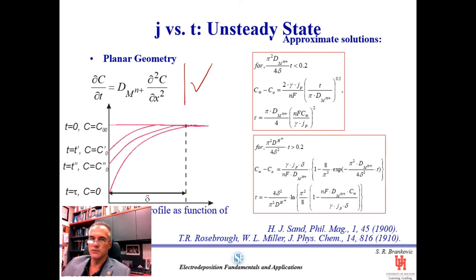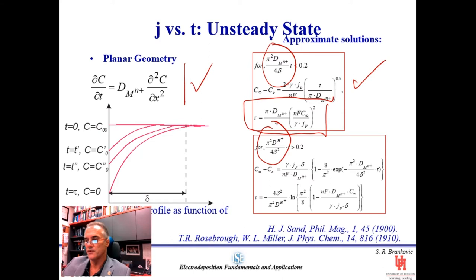So basically, there are two approximate solutions of this problem, which are really truly a function of this term here, whether it's bigger or smaller than 0.2. If it's smaller than 0.2, the Sand equation shows you a pretty good description of the concentration profile at the interface as a function of time. And it gives you a really important parameter here, which we call transition time, which tells you how long time has to pass from the moment you turn on the current for deposition at a constant current value until the concentration at the interface drops to zero.